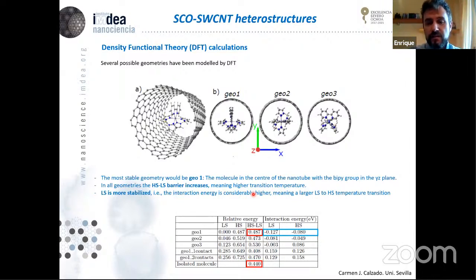In this direction, even more relevant is the interaction energy. She finds that the interaction is much stronger between molecule and nanotube when the molecule is in the low spin state. Okay, this would explain the opening of our hysteresis loop. So once the molecule moves from high spin to low spin, it prefers to stay there rather than going back to the high spin. That's why this second transition is most likely moved to higher temperatures.